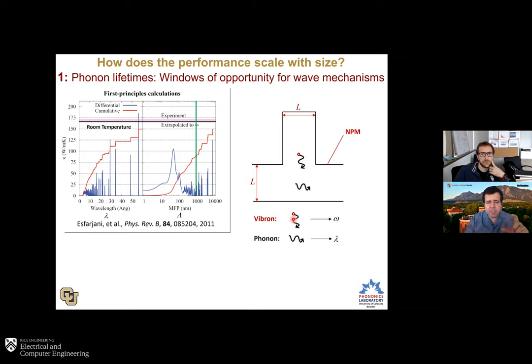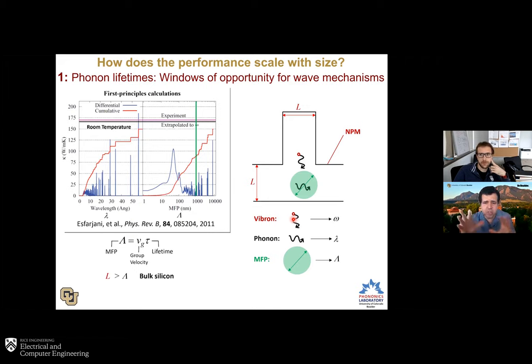So if we were to draw a circle representing the phonon mean free path, we can get that and we can relate it to the lifetime, as I mentioned earlier. If we were to draw a circle that represents the average and draw it within a unit cell of our pillared membrane, our NPM, if this circle happens to be small compared to the feature sizes, then in principle, these features are irrelevant. So we're still talking about bulk silicon, except a huge sample of bulk silicon. Now, on the other hand, if we were to design the features such that they are within that circle, then we are effectively changing the material altogether.